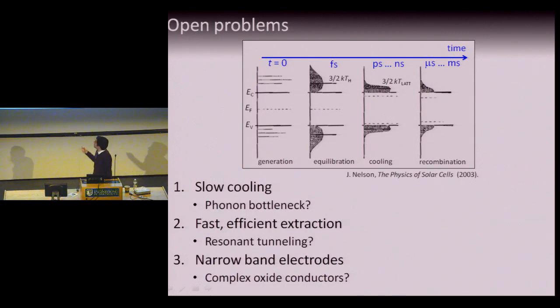So these carriers, these electrons and these holes, equilibrate amongst themselves to form a true thermal distribution on a time scale that's about femtoseconds, so that's 10 to the minus 15 seconds, give or take an order of magnitude. That's portrayed here by a population of electrons with mean kinetic energy, by the equipartition theorem, 3/2 kT. That's T sub hot, I suppose, and that's a number that's close to 6,000 Kelvin. And similarly, you have a population of holes with presumably the same 3/2 kT mean kinetic energy.